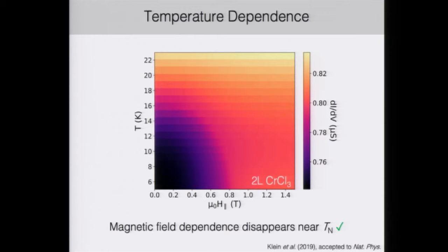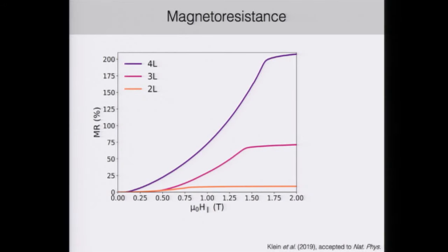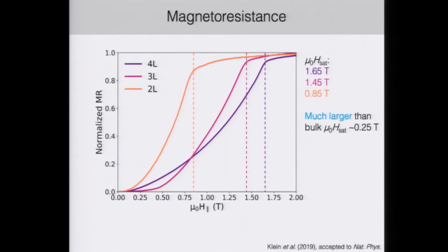Yeah. So far, it looks just like what we would expect for the bulk until you start to look at the magnetic field scales of this magnetoresistance. So here I'm showing the magnetoresistance for 2, 3, and 4 layer devices as a function of in-plane applied magnetic field. And just to normalize them onto the same scale, you can see that these saturation fields indicated by the dashed lines are much larger than what we would have expected based on the bulk chrome chloride data. So the bulk saturation field is all the way down here, yet we're seeing that it's much harder to polarize the spins in the same direction in the few layer limit, indicating that there must be some larger antiferromagnetic exchange between the layers when we go down to the thin limit.